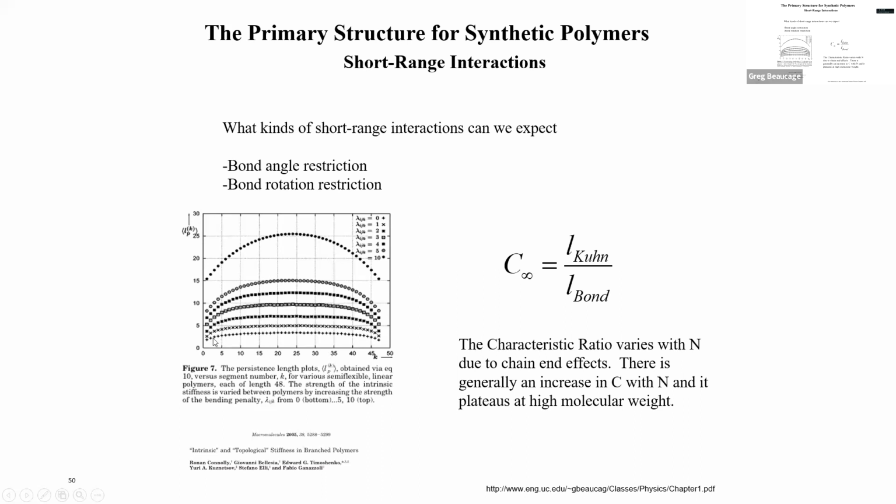Well, as the chains get longer, the endpoint has a lower C infinity than the middle part. So it's going to be C to the N, and then it'll go to C infinity when you get an infinite chain with no N lengths on it, N units on it. And then it's just like what the middle is on average, because the ends are always going to be floppier than the middle. Right, so that means they're going to be more wiggly. They're going to have a lower persistence length.